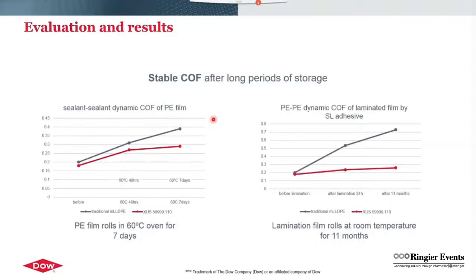Next, the COF of the polyethylene film rolls and the lamination film rolls were evaluated after long periods of storage. The graph on the left-hand side shows the COF of the polyethylene film after the rolls were stored at 60 degrees Celsius for up to 7 days. With the traditional metallocene LLDPE sealant, the COF increased to close to 0.4 after storage. While with the COF stable resin XUS 59999.110, the COF was maintained below 0.3.